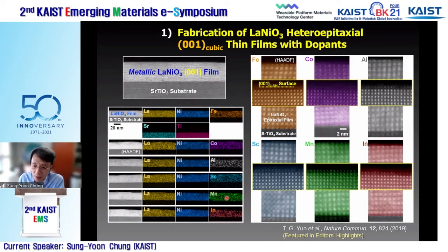Instead of using nanoparticles, we just focused on the utilization of the heteroepitaxial lanthanum nickel oxide film, because nanoparticles have so many different facets. So we cannot understand which one has higher or lower activity. So we use such a heteroepitaxial thin film. That means the surface is always the 001 crystallographic surface, and basically the base material is lanthanum nickel oxide.